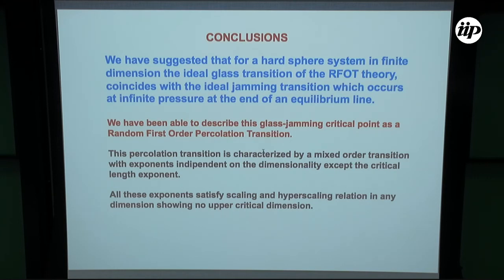So, in conclusion, what we suggest is that for hard spheres in finite dimension, the ideal glass transition of the RFOT theory coincides with the ideal jamming transition which occurs at infinite pressure at the end of an equilibrium line. So we have been able to describe this glass-jamming critical point as a random first-order percolation transition. And this percolation transition is characterized by a mixed-order transition with exponents which are independent of dimensionality, except the critical length exponent nu, which instead depends on dimensionality: nu equals 2 over d. And as you have seen, these exponents satisfy both scaling and hyperscaling in any dimension, showing that there is no upper critical dimensionality. Thank you very much.